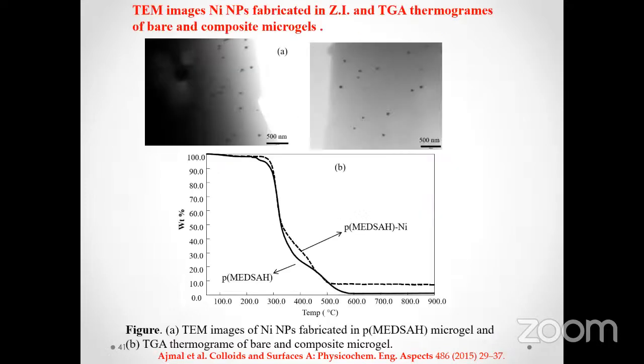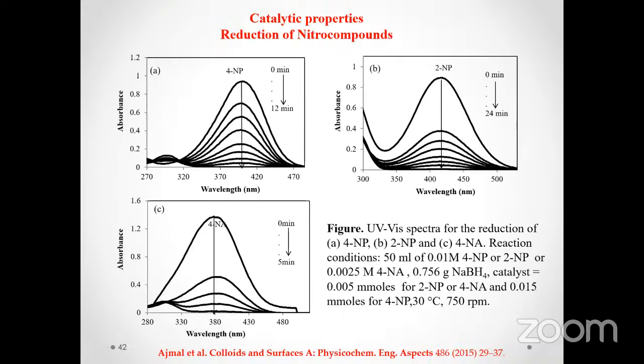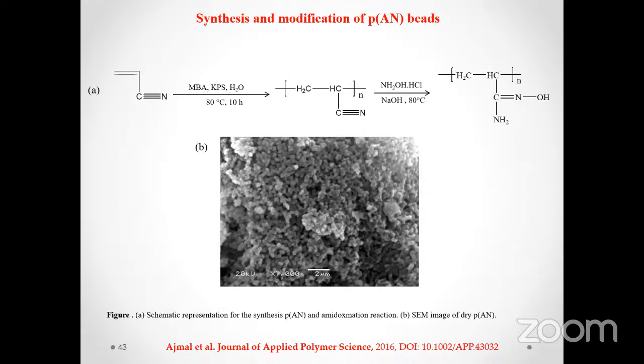And in this case, we have prepared nickel nanoparticles, and very fine, well dispersed nickel nanoparticles were observed, as can be seen from these two figures. And the thermal analysis also shows the presence of some amount of nickel in these composites, and thermal stability of this system above 200 degrees centigrade. Again, the catalytic activity of the system was also very fine for the nitro compounds. And here is another polymeric system.